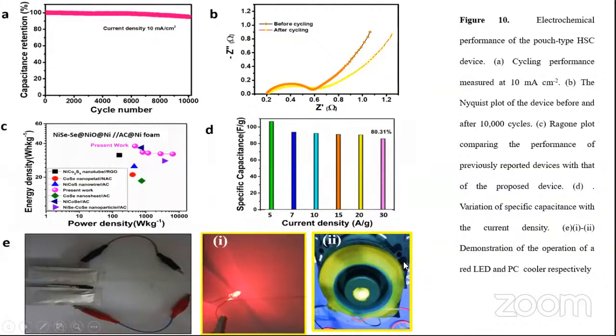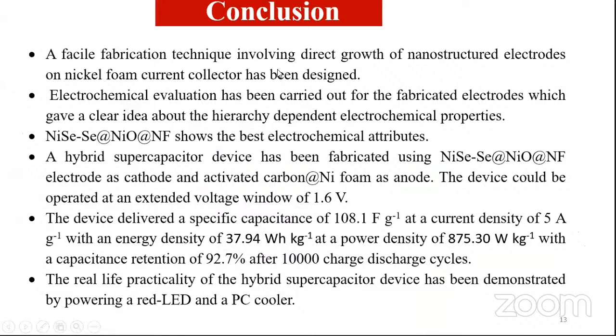So coming to the conclusion, a facile synthesis technique was developed by the direct growth of nanostructured electrodes on nickel foam current collector. Then electrochemical evaluation has been carried out for all the electrodes. NiSe-Se@NiO@NF shows the best electrochemical attributes. A hybrid supercapacitor device has been fabricated taking Ni, Se, NiO composite electrode as cathode and activated carbon as anode, and it worked at an extended potential window of 1.6 volt.